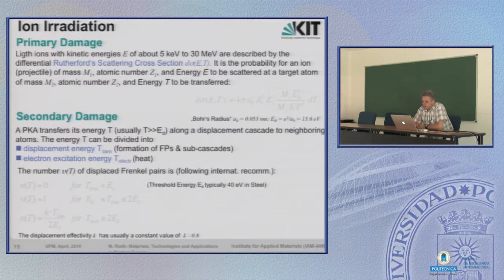Also here, don't worry, it's not important to get all this formula in detail. I will try to show you the global picture. This is the probability for an ion of mass m, or m1 here, with the atomic number Z and the energy E, to be scattered at a target atom of the lattice, which has mass m2, atomic number z2, and which will be kicked off with the energy T. This cross-section is given here. That's the Rutherford scattering cross-section. With this, we describe the primary damage. The secondary damage, where a PKA, a primary knock-on atom, transfers its energy T along a displacement cascade to the neighboring atoms.